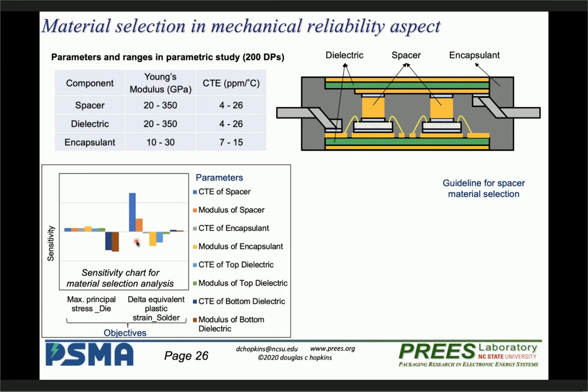So let's see an example. If we want to reduce the plastic strain of the solder, look at the blue column here. We should reduce the CTE of spacer for lower plastic strain because it is a positive column here. So same concept, look at the yellow column here. It is modulus of encapsulant. So it shows that we need to increase the modulus for getting lower plastic strain. So actually, this chart helps us to understand the whole picture, all the interactions in terms of the mechanical reliability.